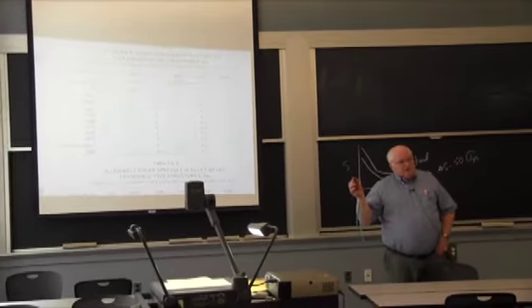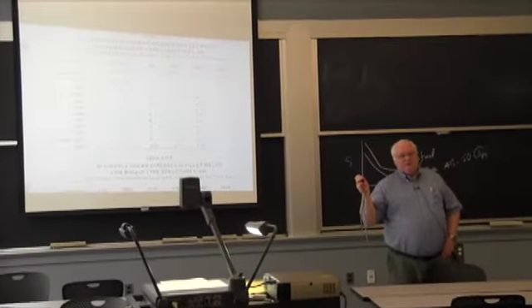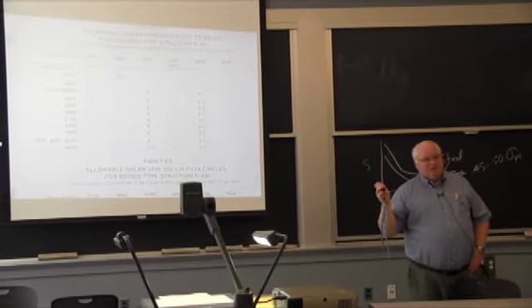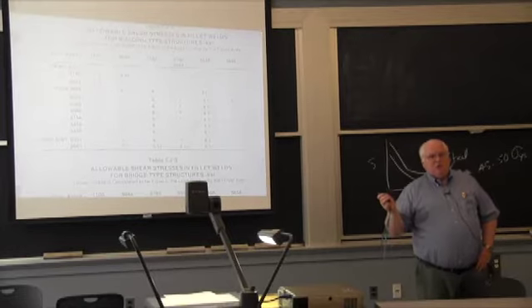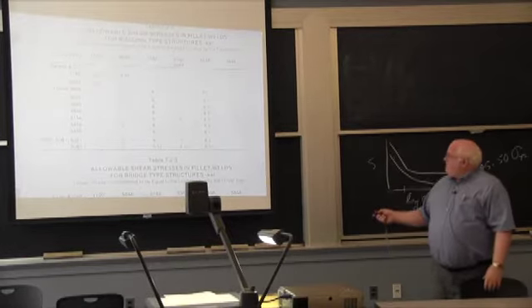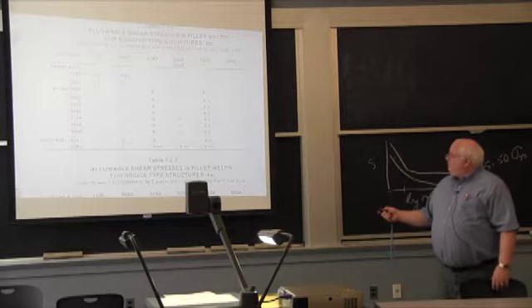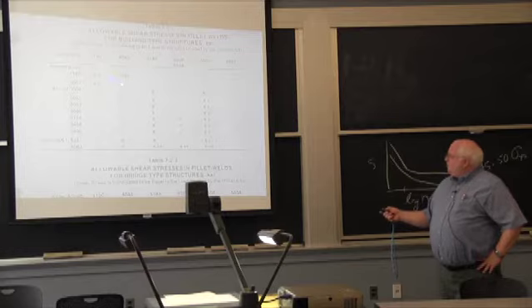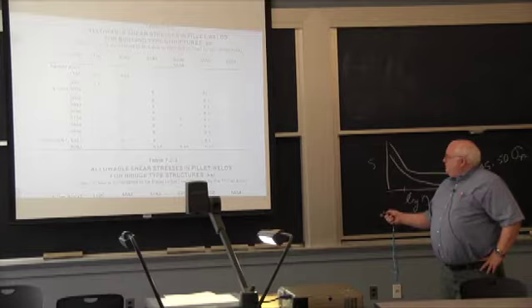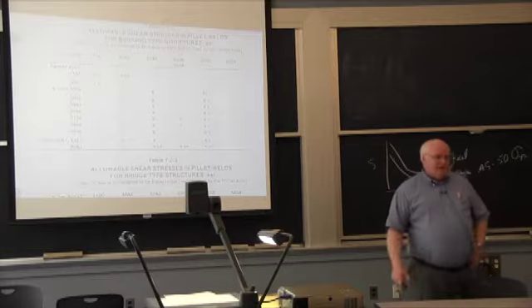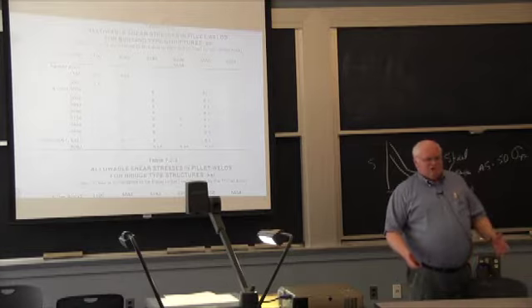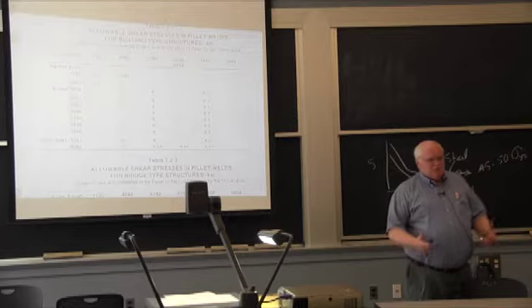But instead of being able to use about 60% of that, which you can in steel, you can only use 1/3 of that. So you're getting down to design stresses in some cases of, well, 1100s, like frying pans. It's relatively pure aluminum or aluminum foil. But you're getting down to design stresses of 5 to 6 to 8 KSI ranges, which is not much stress at all. It's not much more than the yield strength of a good plastic.